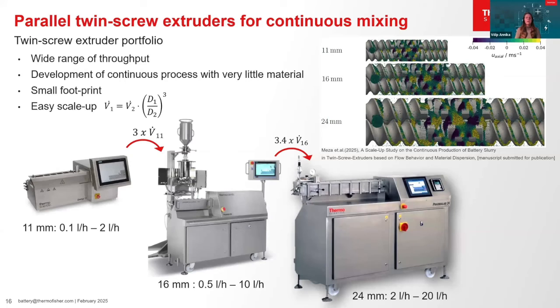On the next slide, the different sizes of Thermo Fisher Scientific twin screw mixers are presented. The smallest is the tabletop Process 11 with 11 mm screw diameter. Besides that, also larger twin screw mixers with 16 mm and 24 mm screw diameters are available. This portfolio covers a material throughput range from 100 milliliter per hour to up to 20 liter for battery slurries. Unlike production scale twin screw mixers, they are easily operated by just one person and require very small sample volumes and are scalable to larger sizes.